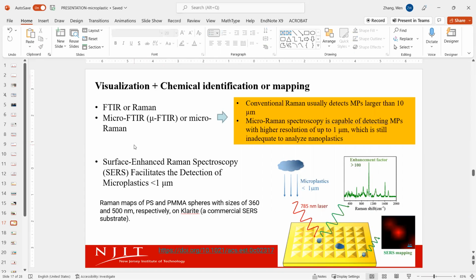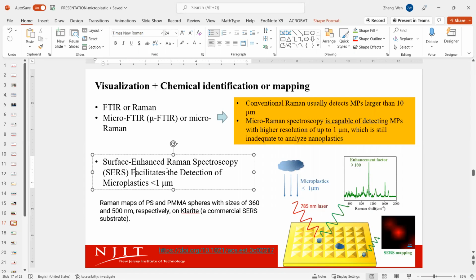So as opposed to regular Raman or IR, here I want to say there are a few techniques. For example, this is called surface enhanced Raman spectrometry. Remember the previous slides I showed you, where people use silver nanowire as a filter to capture the plastic particles. That technique relies on so-called surface enhanced Raman spectrometry, where on your substrate you need gold or silver elements to enhance the Raman signal coming from your samples.